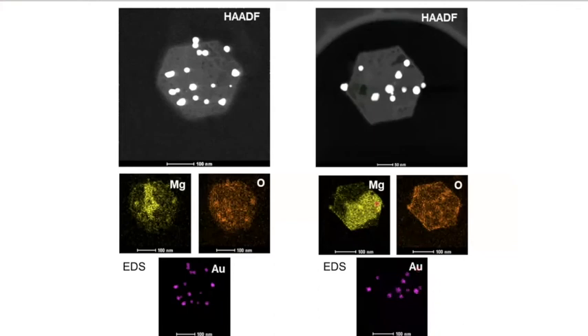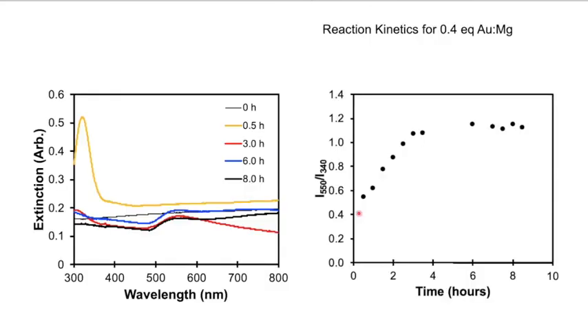Some of the magnesium, of course, gets etched and turned into magnesium oxide. Some of the magnesium remains as metal in here. We can track this. Jeremy has done really beautiful work on that. This is, for instance, the reaction kinetics with gold. And this is really quite easy